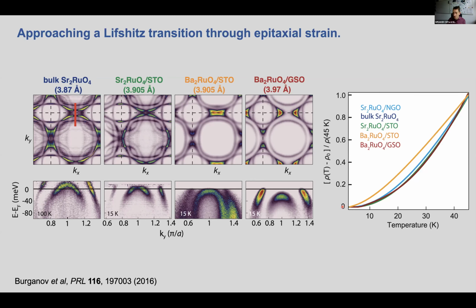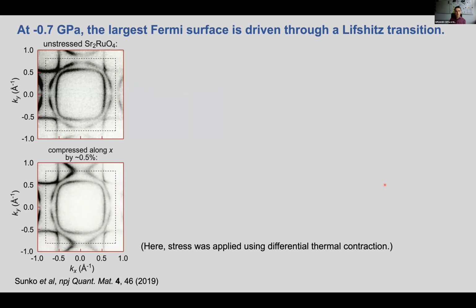When they look at transport properties, this is the resistivity as a fraction of its value at 45 Kelvin versus temperature. All of these films show good approximately T-squared resistivity, except for this one, the barium ruthenate on strontium titanate. This one right here has a power law of about T to the 1.4. So approaching this Lifshitz transition affects the transport properties quite strongly.